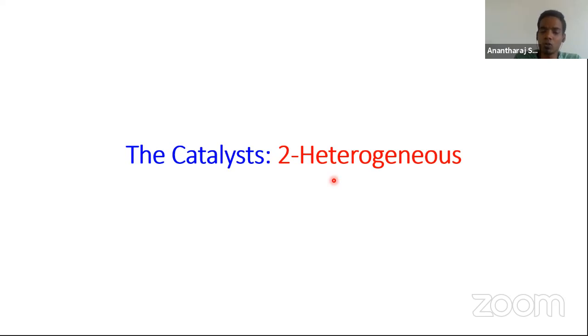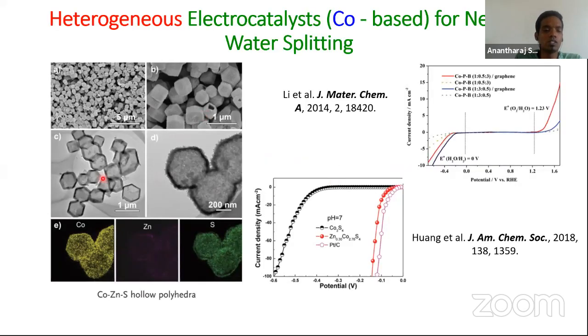So let's see a few examples of such electrocatalysts that were applied recently for neutral water splitting. The very first one is the zinc cobalt sulfide hollow polyhedra. This was very recent work, and you can see just cobalt sulfide for hydrogen evolution reaction at pH 7, I mean, in PBS, phosphate buffer solution, the over potential is way higher. But when a simple zinc is added in this ratio to the parent cobalt sulfide, it delivered almost parallel activity to that of Pt/C. So this was the very first time that neutral water reduction for hydrogen generation could be done even without having a common ion, because before this, every work on neutral water oxidation was said to follow a single rule in which the catalyst must have a common anion to that of the electrolyte. So this was the first report that refuted such a rule.